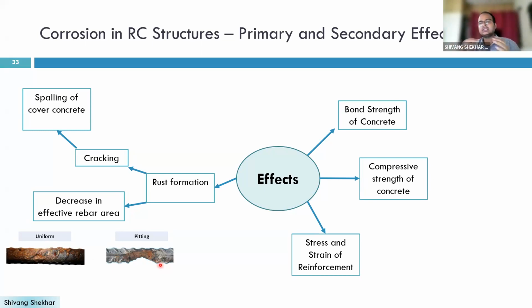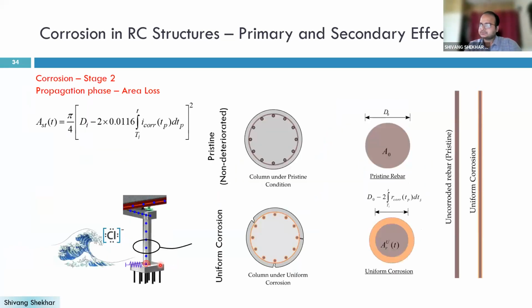There are several other secondary effects of corrosion too. When the cross-sectional area reduces, the rust that forms expands, and that leads to cracking of the cover concrete. There is a bond strength reduction, and the compressive strength of the cover concrete also gets reduced. Then there is a change in the stress and strain of the reinforcement. So there are different effects of this corrosion.